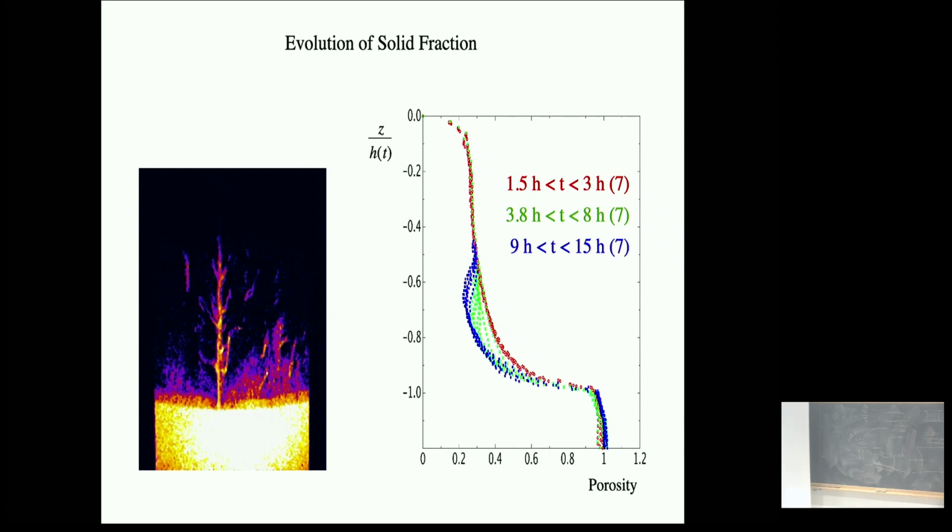Okay? Another way of thinking about it is we take this very salty brine out through the brine channel into the ocean. It needs to be replaced just because of continuity of mass. It's replaced by relatively fresh water from the ocean coming into the mushy layer, and because it's relatively fresh, some of that water will freeze and increase how much ice there is and reduce the permeability. And if you look spatially, the region over which the porosity is decreased corresponds to the region in which there are dissolution channels, brine channels.